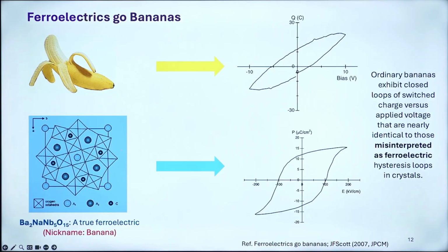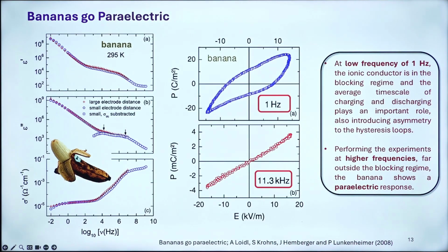So one can say that it is not necessary that if you get a loop like this then we can conclude it is a ferroelectric, and several experimental results were also reported which misinterpreted this as ferroelectric. So I will show one classic example. This famous article by this group in 2008, where they saw this banana, and if you have this kind of loop then we cannot conclude that particular system to be a ferroelectric.